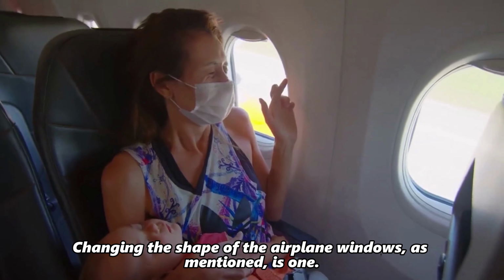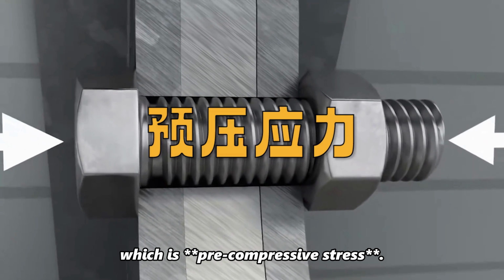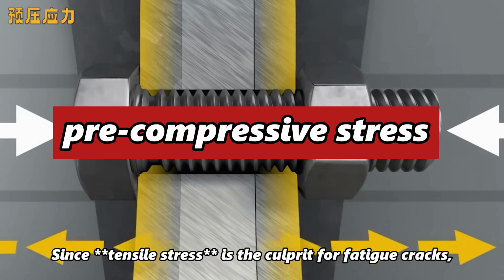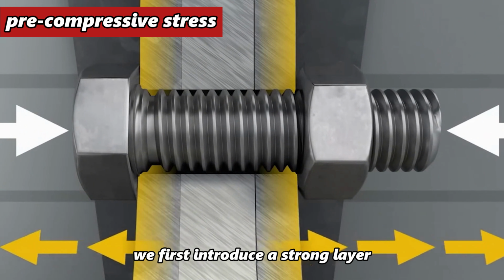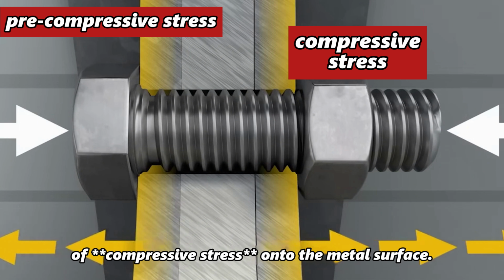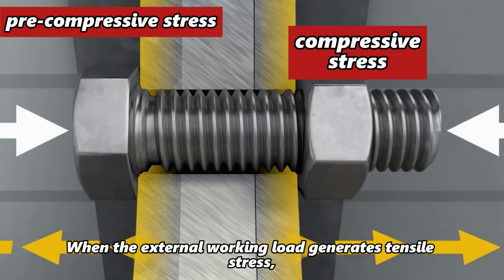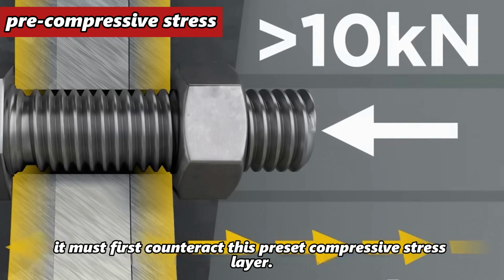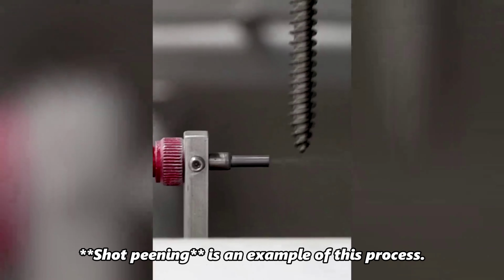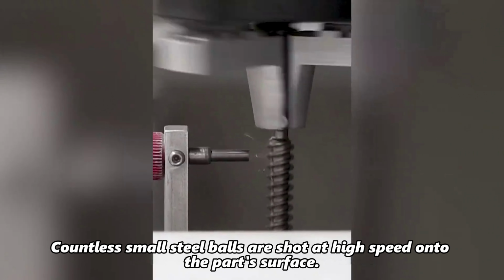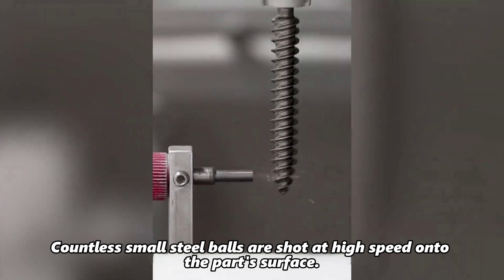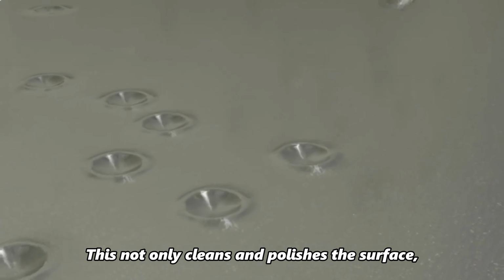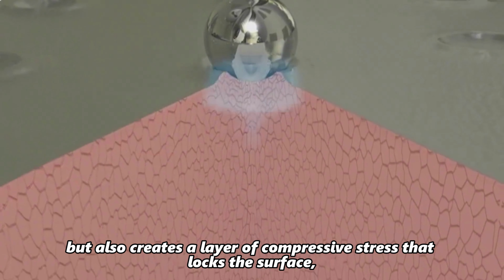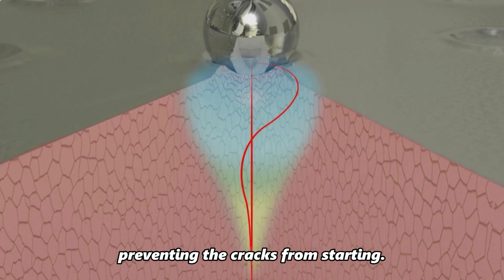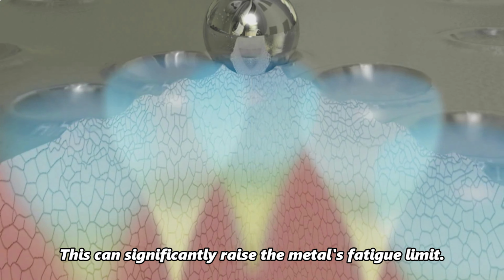Changing the shape of the airplane windows, as mentioned, is one. Another is a method of fighting fire with fire, which is precompressive stress. Since tensile stress is the culprit for fatigue cracks, we first introduce a strong layer of compressive stress onto the metal surface. When the external working load generates tensile stress, it must first counteract this preset compressive stress layer. Shot peening is an example of this process. Countless small steel balls are shot at high speed onto the part surface. This not only cleans and polishes the surface, but also creates a layer of compressive stress that locks the surface, preventing the cracks from starting. This can significantly raise the metal's fatigue limit.